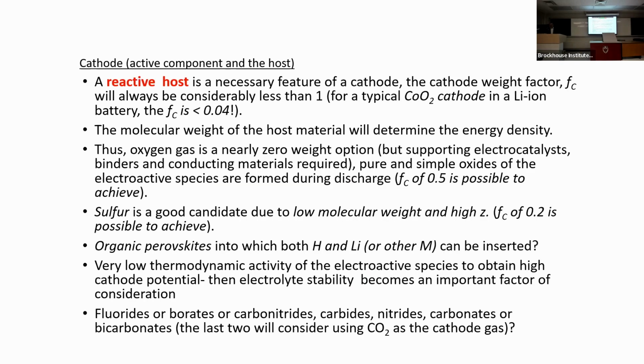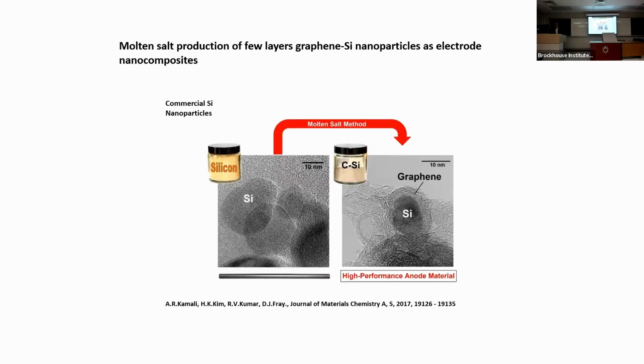Cathode, whatever you do, your question? Just back last slide. You didn't say under graphene, the expansion of silicon is open, or is it just kept in check? Kept in check. You cannot, it's a good question. You cannot do away with it. Once lithium reacts with silicon, there's a huge volume change, and in the discharge and the charge, the delta V is maxed. As a result of that, it mechanically degrades and loses contact with the conducting particles. But once it's encapsulated like this structure, it is mechanically as if it's breathing. Okay. Thank you.